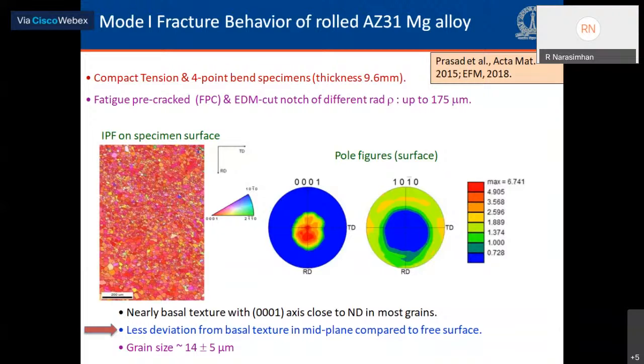What you see on the left side is the inverse pole figure map of the as-polished specimen, and the right side are the 0001 and 1010bar pole figures. The IPF map shows a nearly basal texture with most of the grains having the C-axis along the normal to the flat surface of the notch. But there is some deviation from an ideal basal texture.